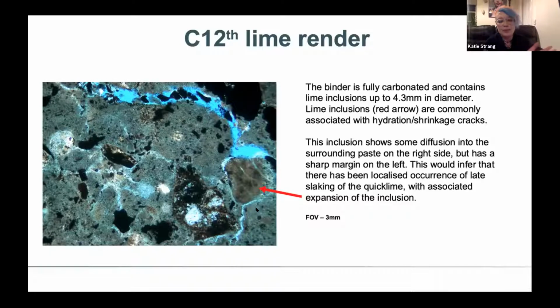So when you burn your limestone, you're removing the carbon dioxide to create calcium oxide. And then you slake that by adding water, and that causes an exothermic reaction where you get calcium hydroxide. Now in a hydraulic lime mortar, there are 2 methods by which it can harden, and one is through carbonation, which is adding carbon dioxide back into your material. So you're basically taking it round the lime cycle back to a calcium carbonate. And that's quite important because those factors influence the hardness and the overall structural integrity of your material.